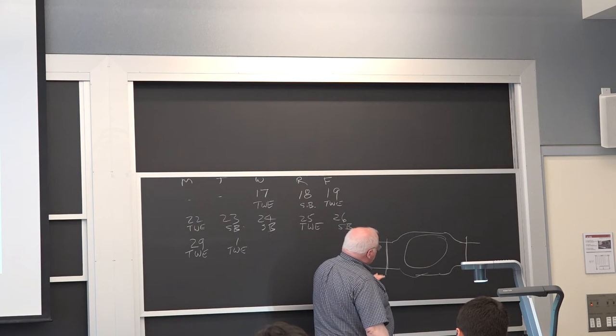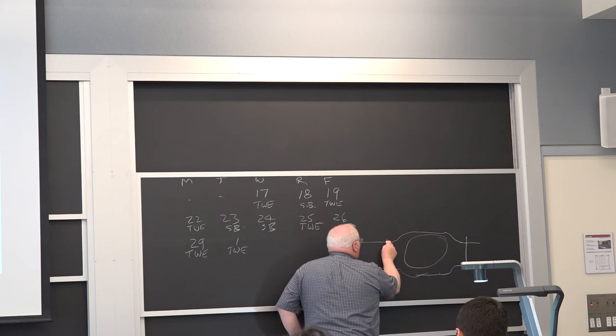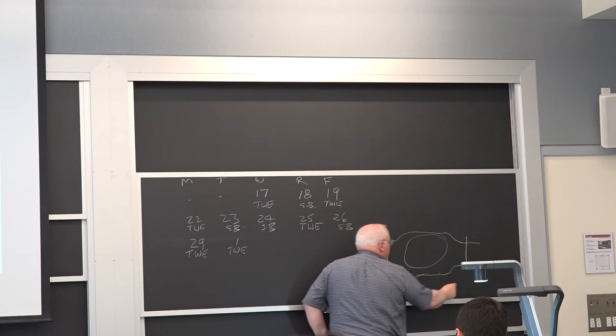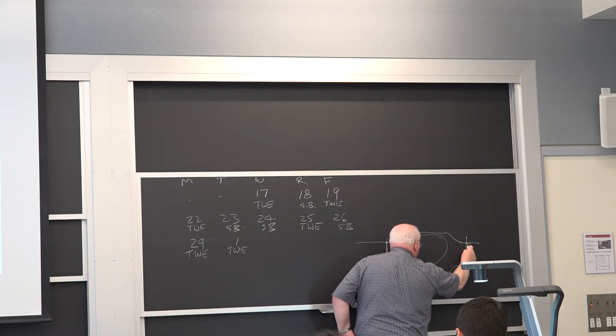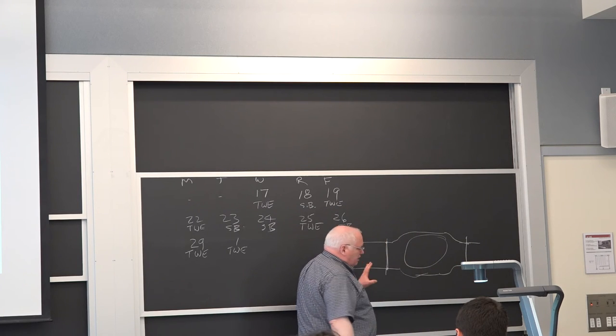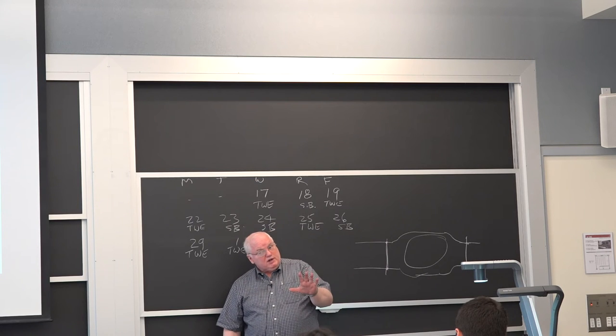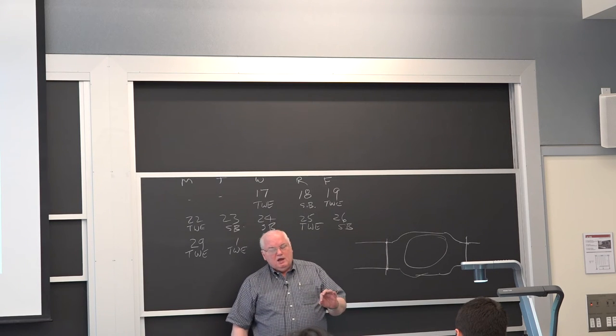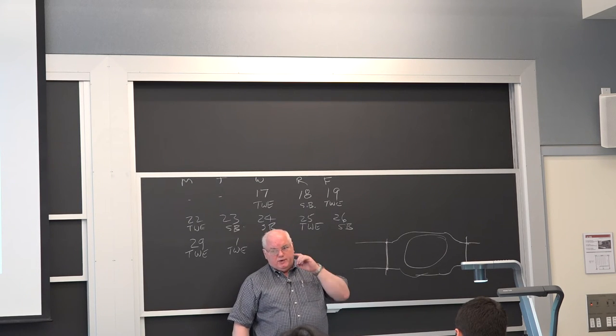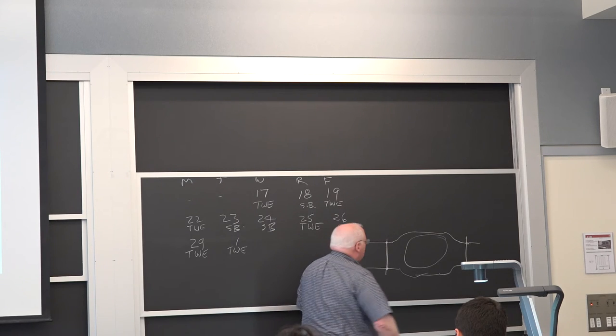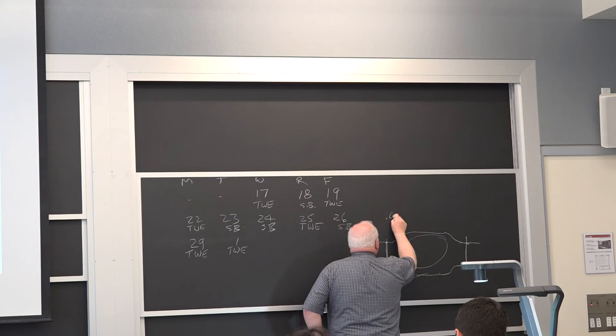That's what Engelhard was doing. They have to make a weld here, 360 degrees around. They have to make a weld over here. So they have to make two welds. And under the general spec for welding of titanium, Boeing had a spec that the welds had to be X-ray inspected and they could not have a flaw larger than 10 thousandths of an inch in diameter, about four human hairs in size.